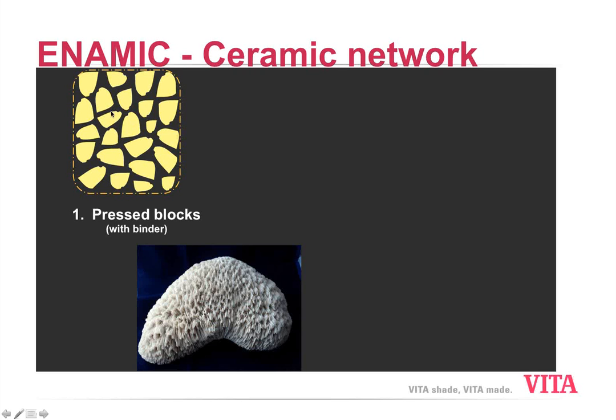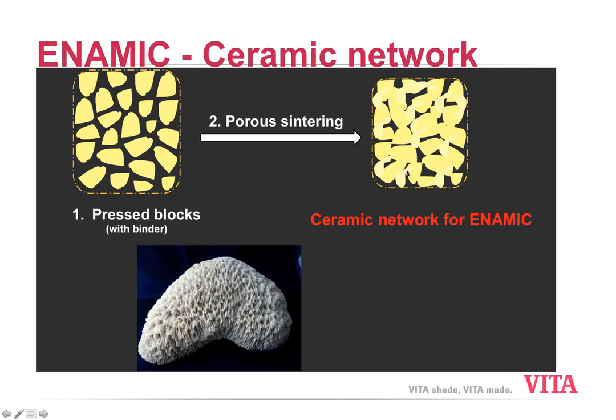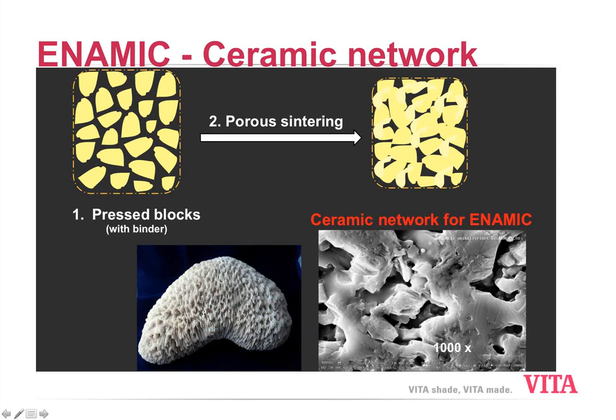So what happens is the powder particles that we're using are pressed into a block. It's fired in an oven, and all these powder particles grow together, sinter together, so that we have an interconnected network like our porous sponge, and this is actually an electron micrograph of that interconnected network. You see all the ceramic essentially is connected to each other, and then all this porosity is also connected. So if you jumped into a pore, you could walk around. I don't know how many hundreds of years it would take you to find your way out, but eventually you could find your way out on the other side if you jumped into the pore.